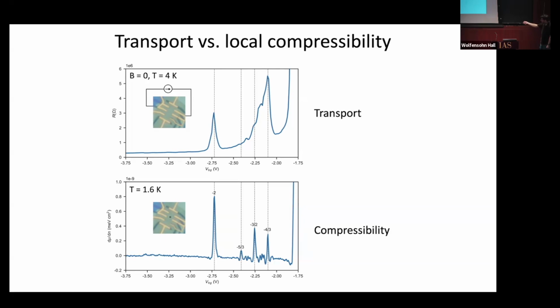But on the other hand, if we park our tip at this black dot here and measure locally what the electronic compressibility looks like, all of a sudden you can see that there are very, very sharp peaks. More of them are resolvable. And the positions actually correspond. So there is some correspondence to the transport measurement, but we pre-screen these devices, and if there are peaks, we say, great, that looks promising, and we couldn't tell you anything about twist angle until we get these local measurements. You can see the dramatic improvement. It's like putting on glasses for those of you who wear glasses.